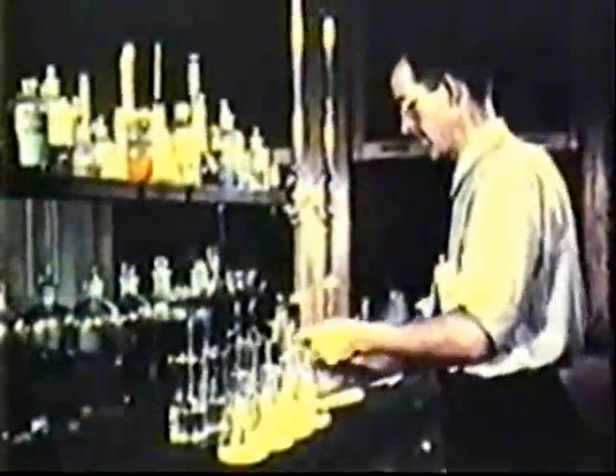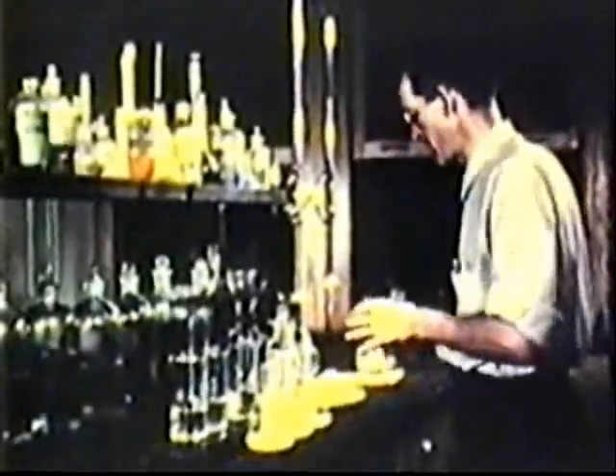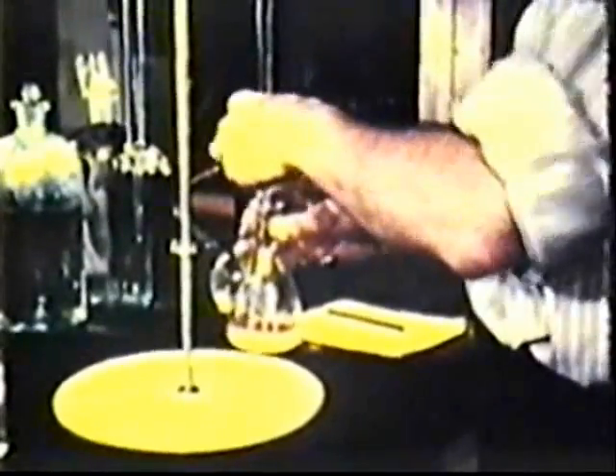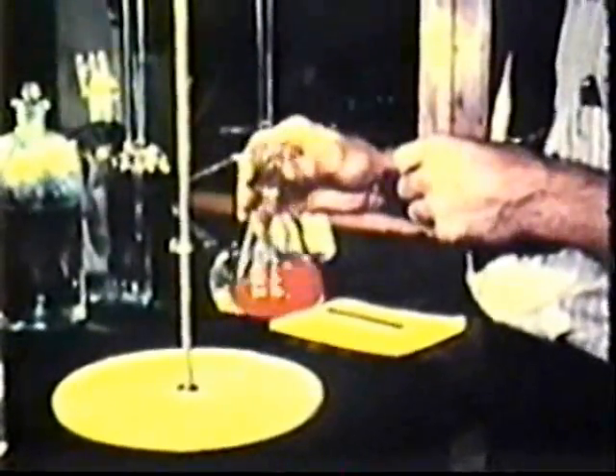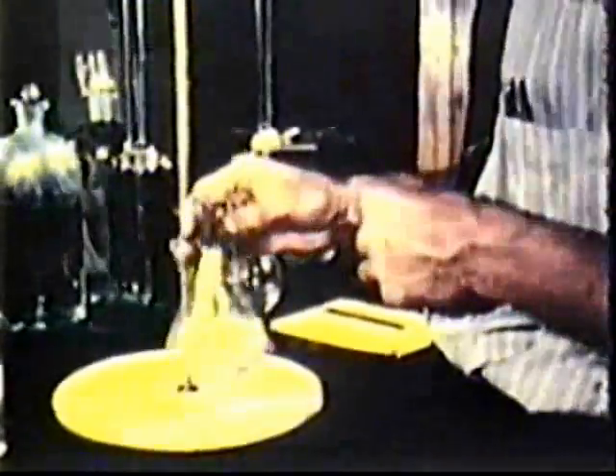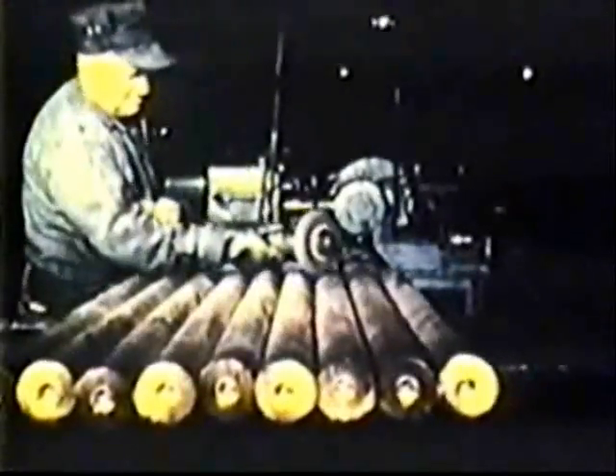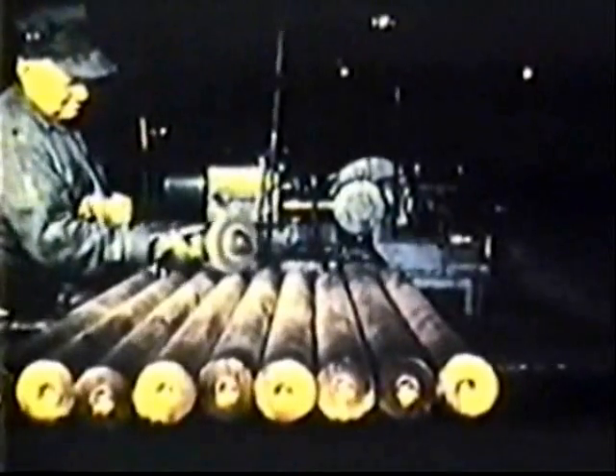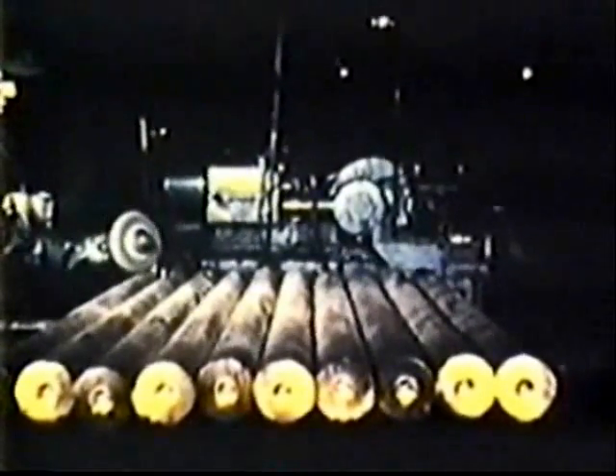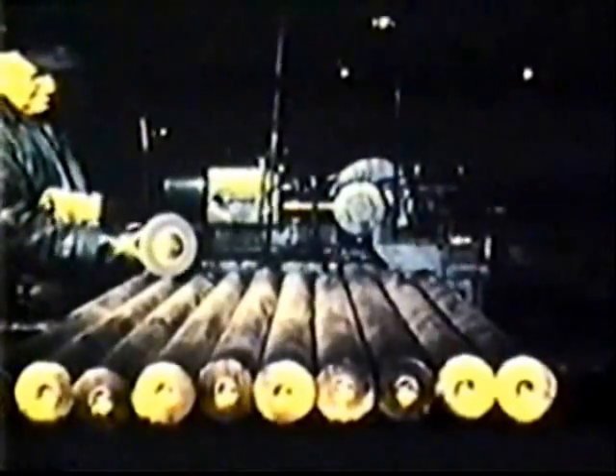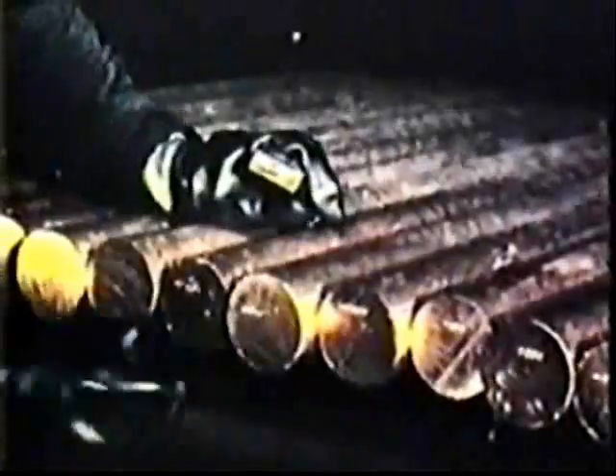Battery assay test, phosphorus determination, titration. These are but a few of the types performed, some of them requiring 2 to 3 days to complete. But without the information gained, there could be no control over the quality of the metal. Therefore, complete reference records are made and maintained on all tests performed. The ends are carefully inspected to be sure they are not porous, and the surface is checked for imperfections. These are removed by grinding. A die mark is made to identify them in the event reference is made to their chemical content.